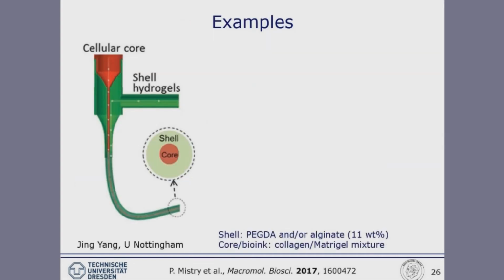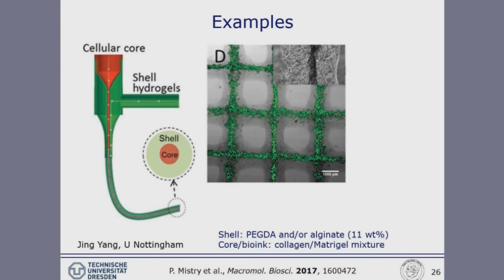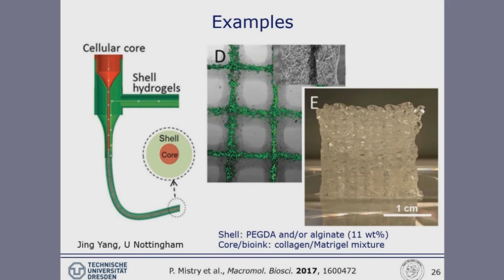Again, a result from literature, a paper published this year by the group of Jing Yang, University of Nottingham, United Kingdom. They have used a quite complicated material combination, a photo-crosslinkable material as shell and a soft collagen Matrigel blend as the bioink, loaded with a couple of different cell types they have tested successfully. And with this, they have printed 3D scaffolds and could show with a live/dead staining that the cells are alive. You can see here the shell material protecting and mechanically supporting the soft bioink with the living cells in the center. And they were able to print really macroscopic scaffolds here with an edge length of 2 centimeters, a cube-like structure.